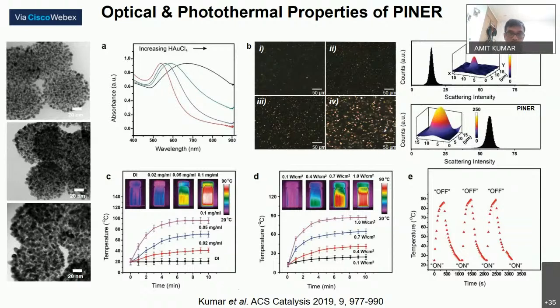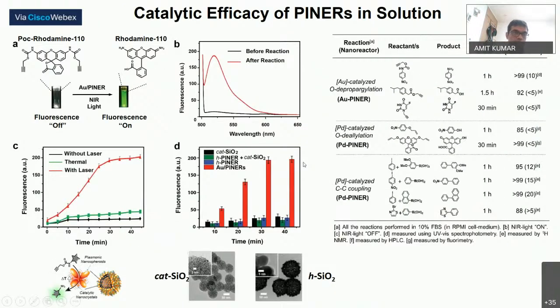As you can see, as the size of the plasmonic corona increases, we observe very high brightness of these structures. And such brightness can be used for bioimaging purposes. As far as temperature increase is concerned, the photothermal temperature can be controlled based on the concentration of the particles and also by changing the laser power. And you can see that under laser irradiation conditions, this switching on and off of the laser shows that the photothermal effect is highly reproducible.